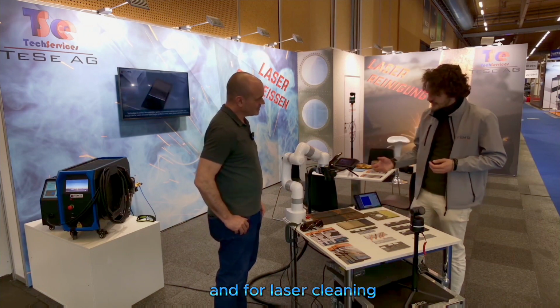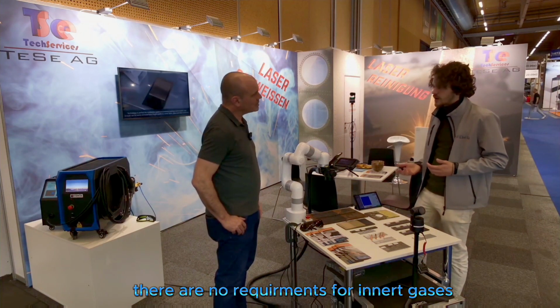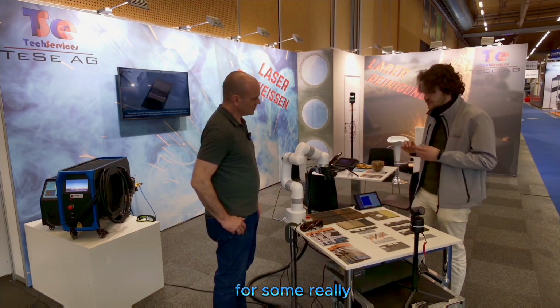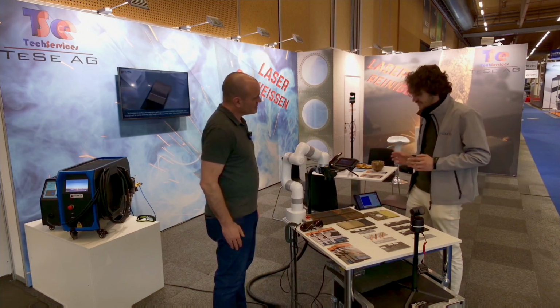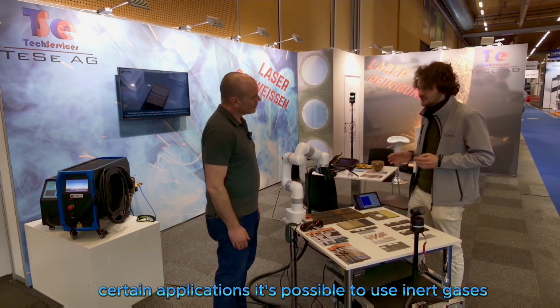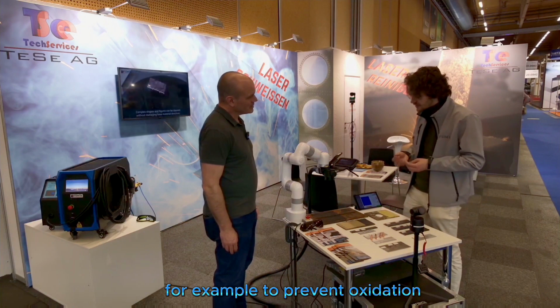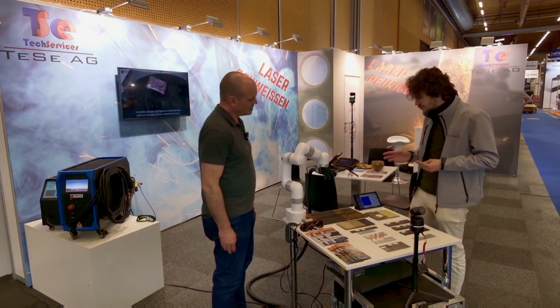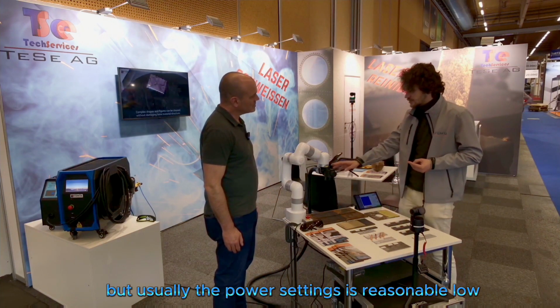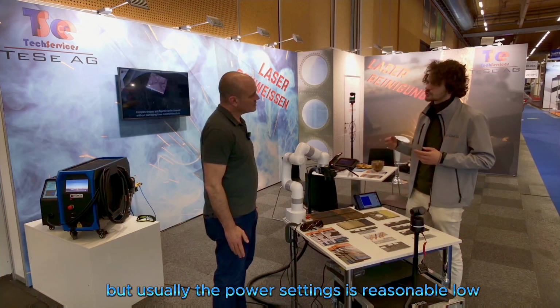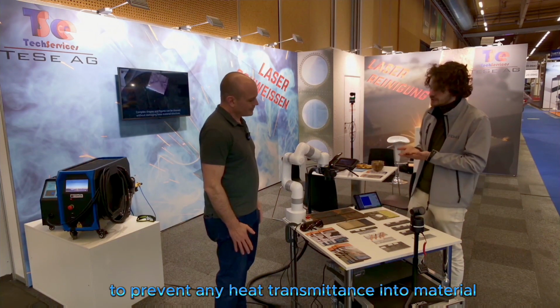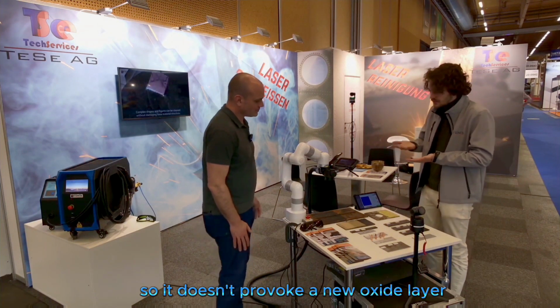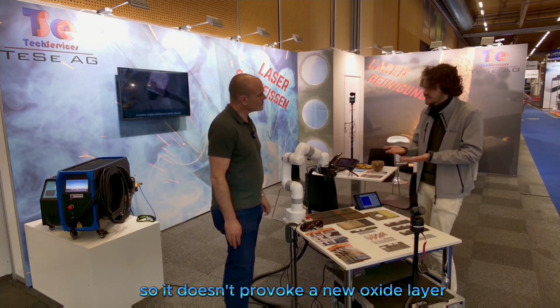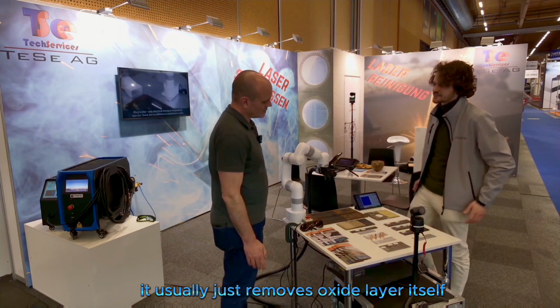And for laser cleaning, there are no requirements for inert gases. Of course, in certain applications, it's possible to use inert gases, for example, to prevent oxidation. But usually, the power setting is reasonably low to prevent any heat transmittance into the material, so it doesn't make a new oxide layer. It usually just removes the oxide layer itself.